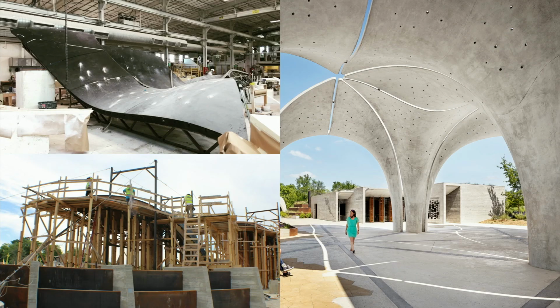Due to the size of each petal formwork, the largest petals were roughly 30 feet wide and 27 feet tall. Each of the modules had to be subdivided into 3 primary subsections, in addition to several side forms, that could be shipped to Texas from California by truck. Although the seams between these sections were nearly seamless due to the excellent casting of the fiberglass, the sanding, and a small amount of caulk applied between the concrete pours, the seams were still designed to accentuate the undulating curvature of the concrete petals.